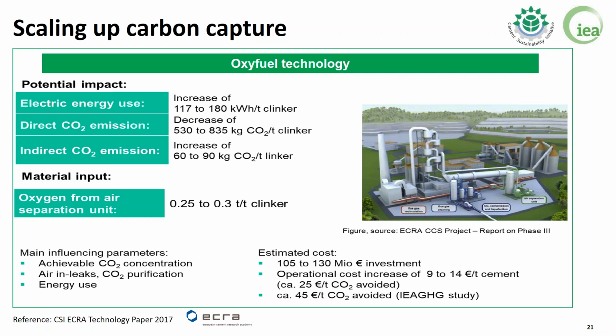But on the other side, due to the fact that oxy-fuel can even capture 100% of CO2 emitted, in terms of direct CO2 emission, there is a decrease of up to 835 kilograms of CO2 per ton of clinker. So the overall CO2 emitted from clinker production. And because of electricity usage, there is a slight increase in terms of CO2 emissions. The quantity of oxygen that is needed for the air separation unit is between 0.25 and 0.3 ton per ton of clinker. Of course, the impacts in terms of CO2, energy and cost depend on the level of achievable CO2 concentration, the level of retrofitting that can be applied to existing kilns in terms, for example, of air leaks in the kiln, and the energy use of the kiln system itself.